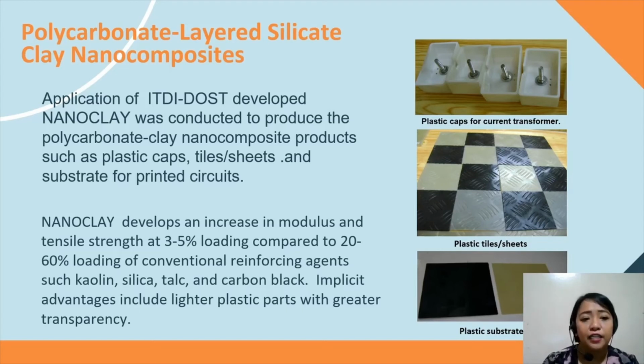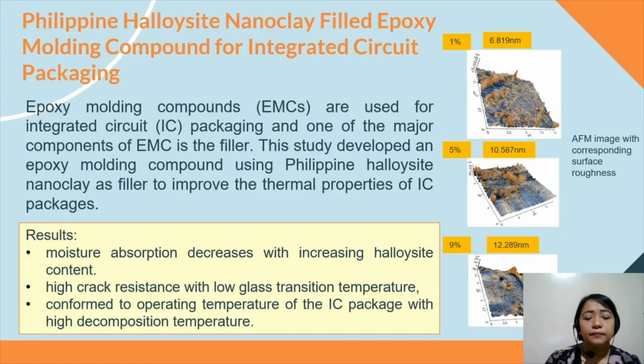Okay, the nanoclay that we developed in the laboratory increases the modulus and tensile strength at 3 to 5% loading compared to 20 to 60% loading of conventional reinforcing agents such as kaolin, silica, talc, and carbon black. So implicit advantages include lighter plastic parts with greater transparency.